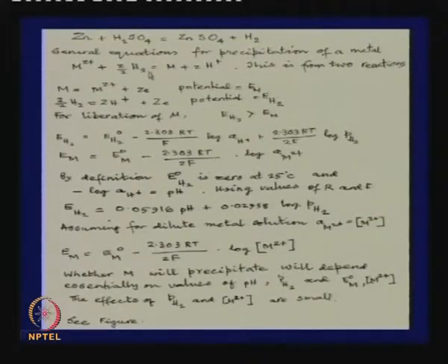But we can make this thermodynamically feasible by increasing the pressure of hydrogen, reducing hydrogen ion concentration, and try to see whether we can push it to the right. This will never be possible for, say, sodium or potassium or cesium, which are so reactive. It does not matter how much hydrogen pressure you apply or how much you lower this down, which means how much acid you make, this will not take place.